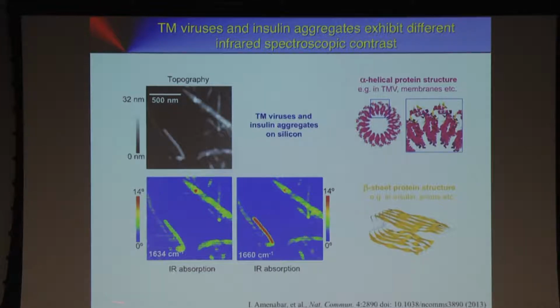So then we took monochromatic images. This is a frequency where we expect the beta sheet to absorb, and we see that all these structures indeed show a strong absorption. Then we switch to 1660 wave numbers, where we know the alpha helical structure is strongly absorbing. Again, all the structures are absorbing, but here we have a particularly strong contrast. It indicates we probably have more alpha helical structure here than in the surrounding.